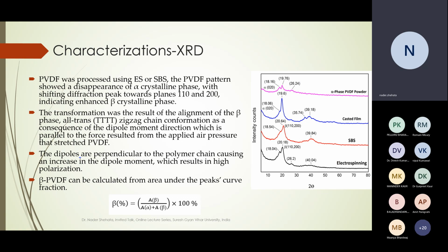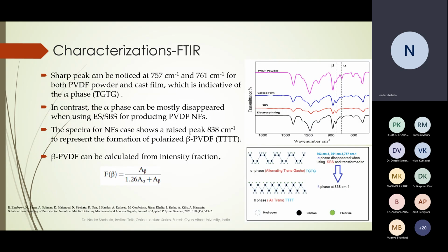And if you'd like to calculate the beta phase content, this is a simple equation to compare the area under the curve of X-ray diffraction between beta phase planes or beta phase peaks and alpha peaks. Whenever you have a higher percentage, up to 100%, then you have more beta sheets, and consequently your material will be more piezoelectric. Okay, in the literature, the maximum one could reach, to the best of my knowledge, does not exceed 90% in some cases, which is a majority of beta phase.